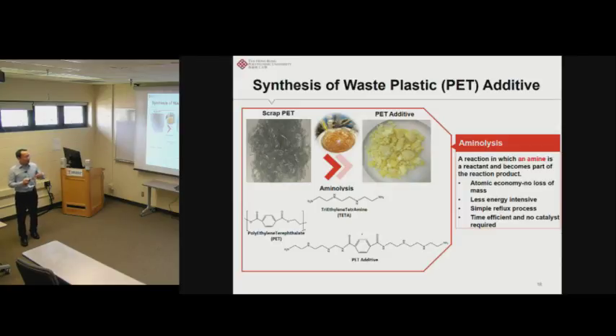The reason why we select this process is, first, this process is considered atom economical. Why is it called atom economy? This is because after the chemical reaction, we will not lose any material, we will not lose any reactant. Everything we used for the reaction will become the final product, and the leftover we can continue to use for further chemical treatment. Also, this process is relatively less energy intensive. We do need some heating for the reaction, but we only need to heat it to around 80 degrees C, not a very high temperature.